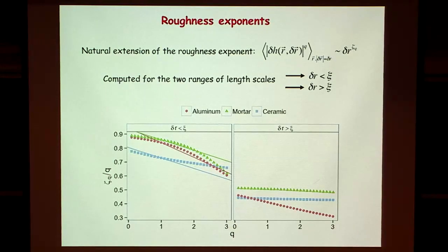So when I think about this result, it makes sense. You have a higher length scale at which your exponent is controlled essentially by elasticity, and a smaller length scale at which it's controlled by the process zone. You can pick out the process zone size, which we know exists in these materials.